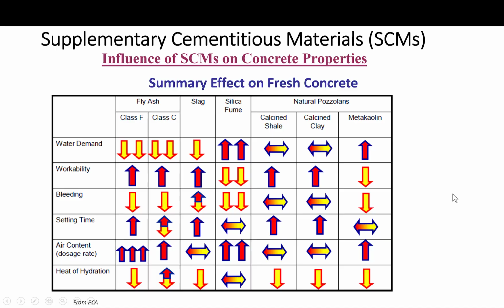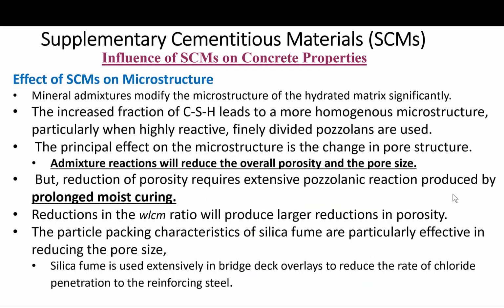Let's move on and see how these mineral admixtures or supplementary cementitious materials impact the microstructure. Mineral admixtures modify the microstructure of the hydrated matrix quite significantly. The increased fraction of calcium silicate hydrate, due to the pozzolanic reaction, leads to a more homogeneous microstructure, particularly when highly reactive, finely divided pozzolans are used.